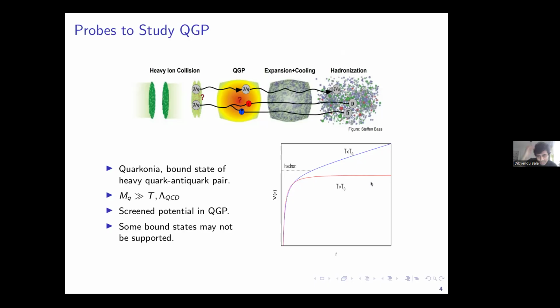The reason for this, the interaction with the QGP, can be understood in the following way. The mass of this quark is much greater than T and the non-perturbative scale Lambda QCD, and therefore you can define a potential between this quark-antiquark pair. Here this curve is the potential below Tc, when there is no quark-gluon plasma. It shows a confined behavior, with a linearly rising string tension, and you can calculate a bound state problem within the Schrodinger equation and find a hadron-like quarkonium. But once you are above Tc, you would expect this potential to get screened because of the other medium, and this bound state is no longer supported. Therefore there should be a decrease in the number of J/psi in the quarkonia in the medium.